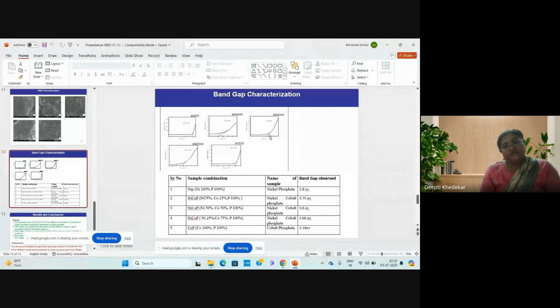These are the band gap characterization. We performed band gap characterization for these 5 samples, and here we got the band gaps. First, for 100% nickel, we got 2.8 electron volt band gap. For 75% nickel and 25% cobalt, we got 3.75 electron volt. Nickel 50 and cobalt 50, we got 3.6 electron volt. Then 25% nickel and 75% cobalt, we got 2.68 electron volt band gap. And cobalt 100, we got 2.18 electron volt.